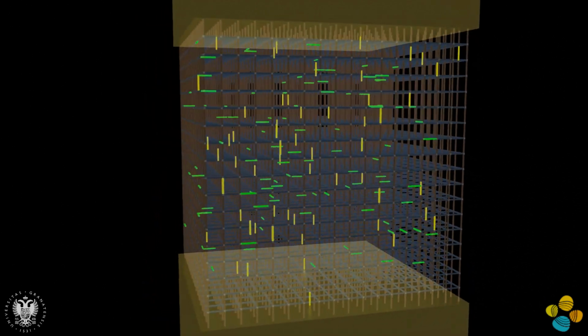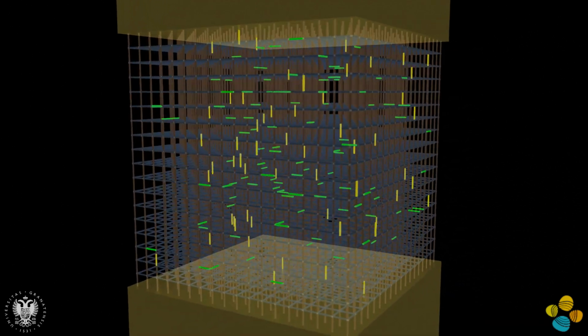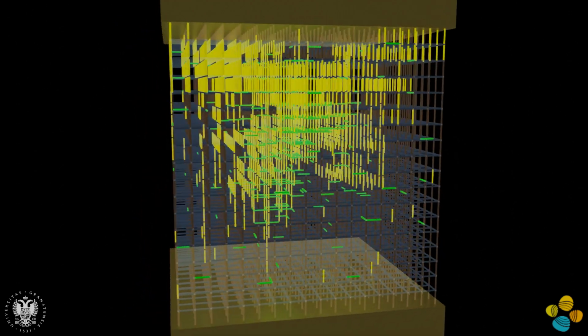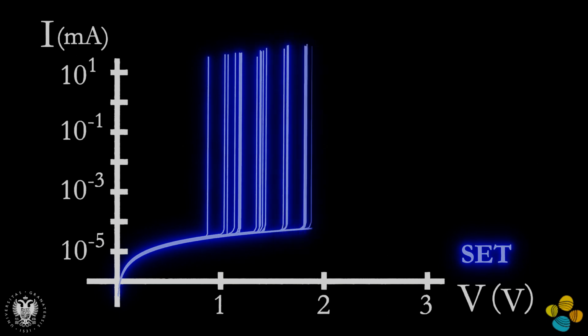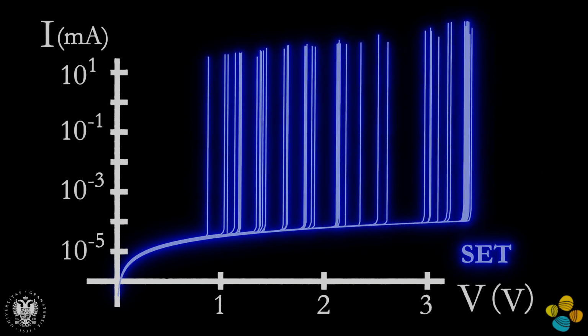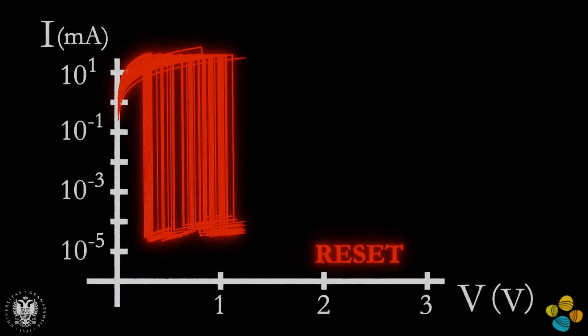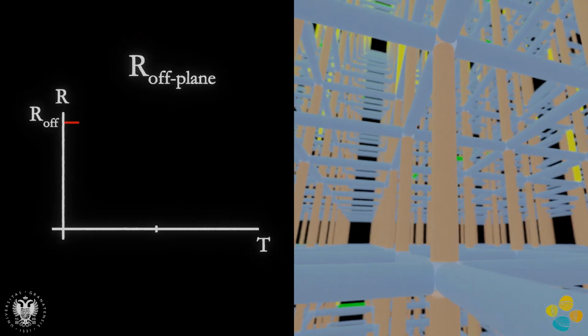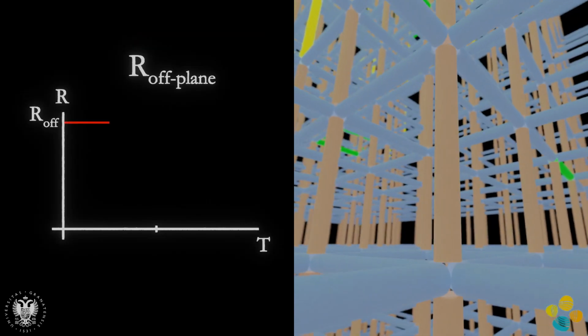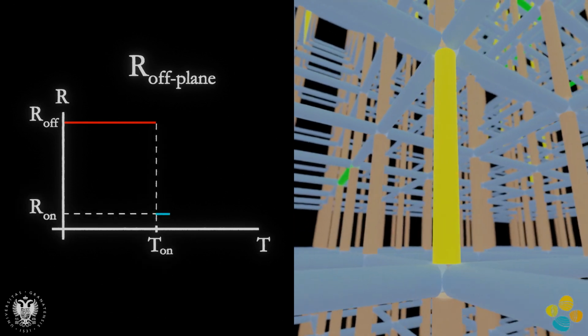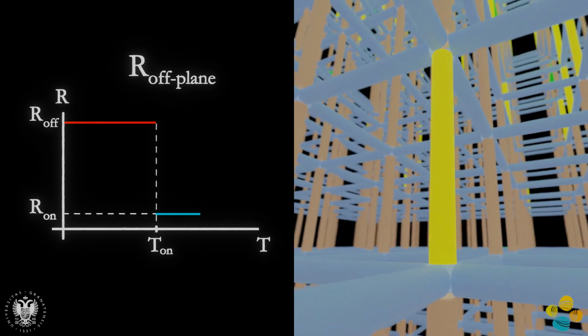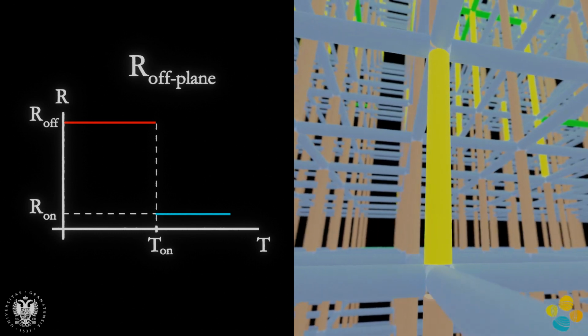Charge conduction is filamentary, and once the filament is formed, a reset process begins. A long series of cycles formed by successive set and reset processes can be simulated. For the switching of the circuit breakers, a similar approach can be followed using the temperature calculated on each resistance in the network. A threshold temperature is defined to switch the resistor.